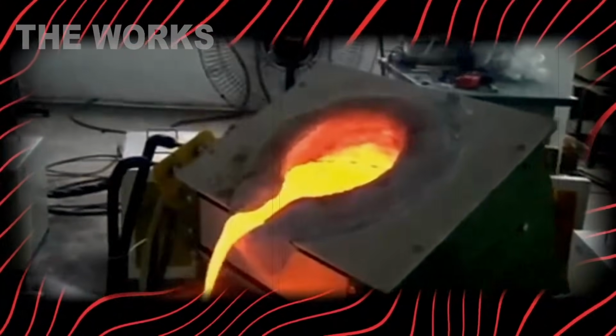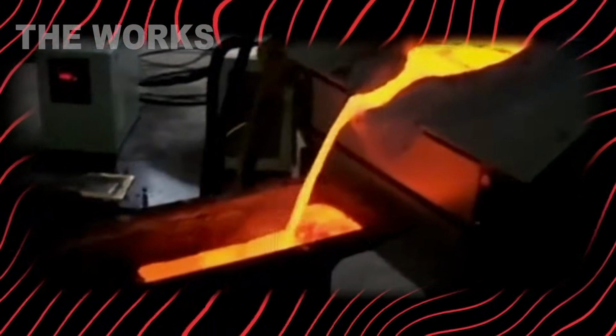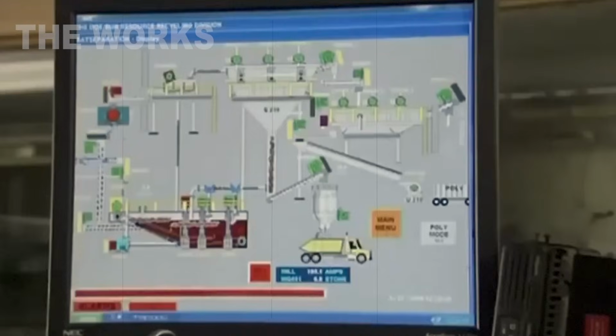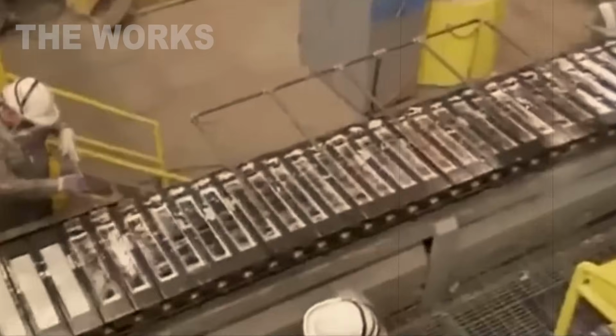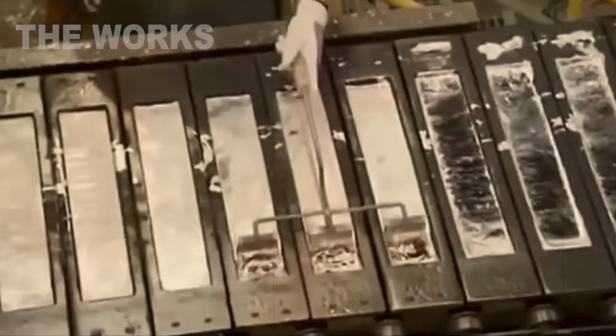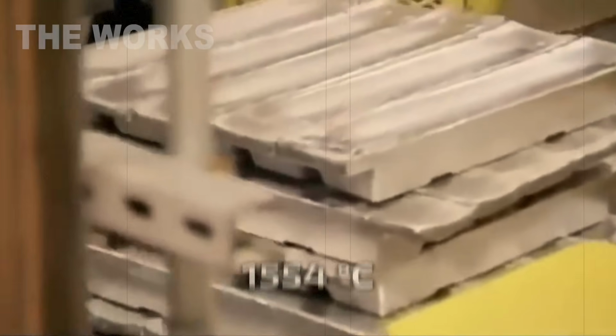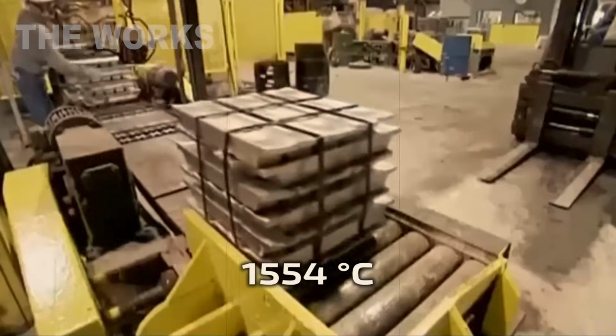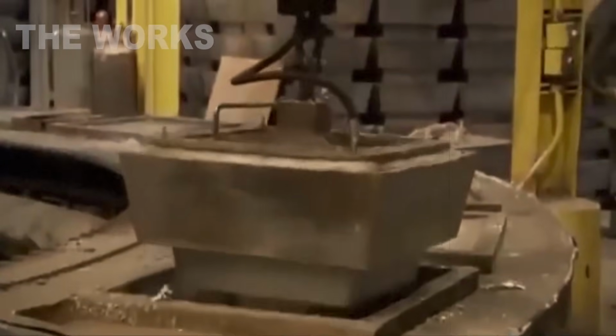Silvery white with a slight steel tint. Palladium's softer than platinum, so you can roll it, forge it, draw it into wire. Palladium's melting point? 2,828 degrees Fahrenheit, lower than platinum. Density? About 0.43 pounds per cubic inch, lighter than platinum, but still a seriously heavy metal. Palladium doesn't tarnish in air, doesn't react with most acids, only dissolves in aqua regia and hot concentrated nitric acid, corrosion resistant. But here's the key property: catalytic activity.